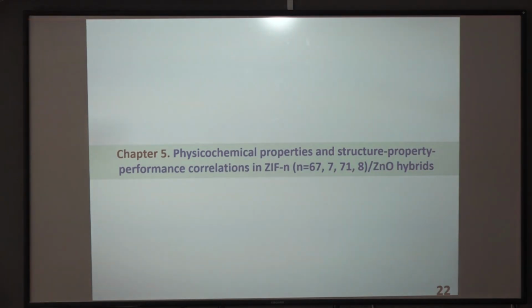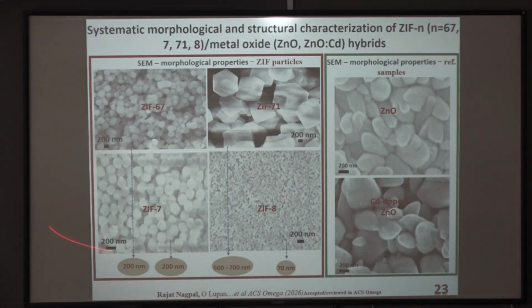Coming to chapter 5, which involves physico-chemical properties investigation of a variety of ZIFs on zinc oxide hybrids and establishment of its structural property performance correlations. Here we can see SEM images. SEM analysis gives insights about the morphology; rhombic dodecahedral morphology for all the particles can be observed, along with particle size estimation. Going to the reference sample, here we can see zinc oxide and cadmium doped. Zinc oxide shows columnar grains coming out of the plane, and in case of cadmium doping, additional columns come out of the existing plane due to the cadmium doping effect.